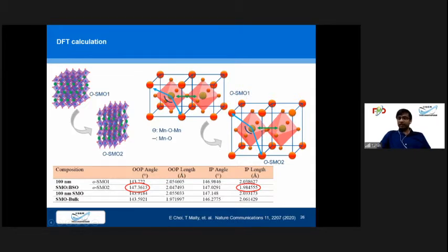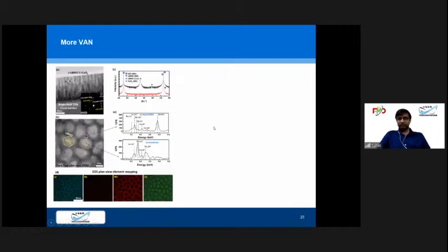This is a small change, but in a single crystal this will affect hugely, because these are spin driven materials. So their whole spin configuration has been modified due to the Mn-O bond angle and Mn-O bond length. So what is happening is that this atom and this atom have become closer, and the interaction between them has increased, and that's why the functionality, or the room temperature ferroelectricity, has been observed.